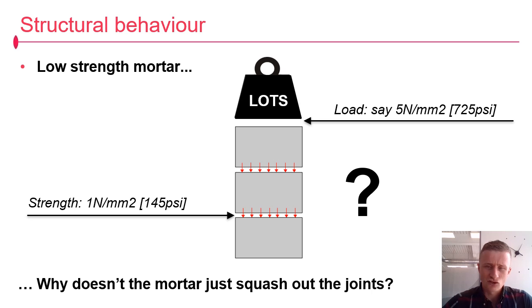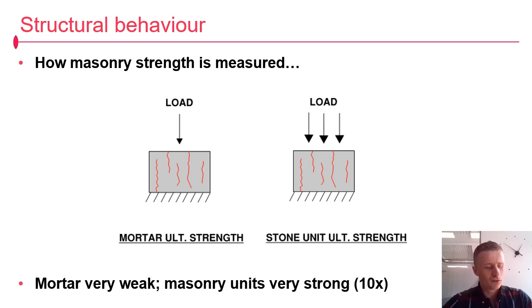So when you look at the stress transmission across the mortar joints, you're thinking, okay, well, if my mortar's only good for 1 Newton per square millimetre and I load it up with 5, why doesn't the mortar just squash out the joint? It's a silly question, but it's got a complex answer. Now, it pays to look at how the strength of masonry is measured. So if you cast a cube of mortar and load it up in a crushing rig, as it approaches its ultimate strength, it tears itself into vertical strips. And those vertical strips are wee side-by-side columns that then buckle. And when they buckle, it collapses. And that's the ultimate strength reached.